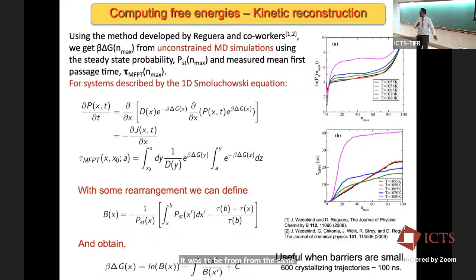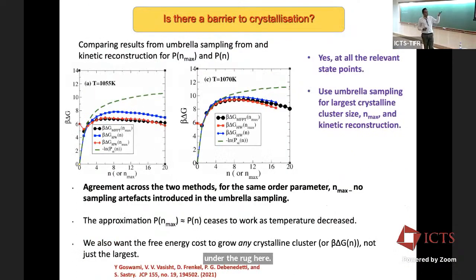Yeah, no, that's usually something that's swept under the rug. Here it's not. It's something that you can calculate. And indeed, in the crystal nucleation problem, the D of X, where X is the degree of crystallinity, is a function of the size of your nucleus, right? Because it depends on the attachment surface area. Yeah, okay.